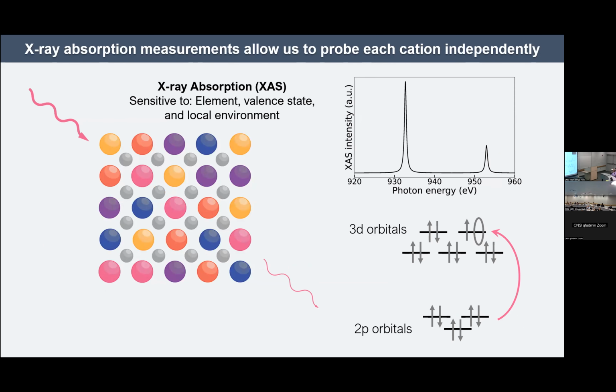Okay, so this brings me to my new favorite technique, which is X-ray absorption spectroscopy, which we've been performing at the Canadian Light Source in Saskatoon. If you're not familiar with X-ray absorption, the basic idea is that we can change the wavelength or the energy of our X-rays, shine them on our sample, and then measure how many of those photons are absorbed by the sample versus transmitted. If there is an allowed electronic transition or excitation in the material, then we'll see a peak in the absorption, because that's where X-rays with those energies are going to be absorbed.